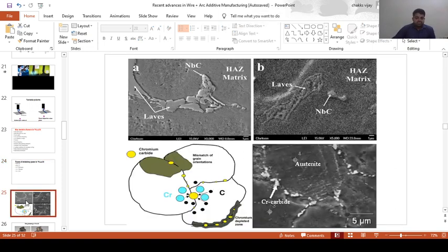Okay, here we can observe this kind of lattice formation, which is a hard niobium shell, an irregular L-shaped shell. Inside this shell, a lot of potential minerals like molybdenum, chromium, and a few other materials are entrapped inside this hard martensite shell. Obviously it will lead to demineralization, which may cause easy corrosion attack. This could be avoided by increasing the cooling rates of the material.